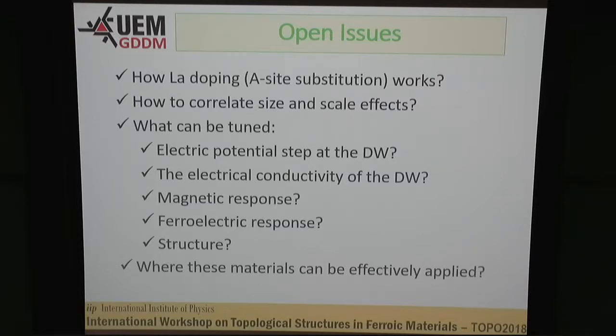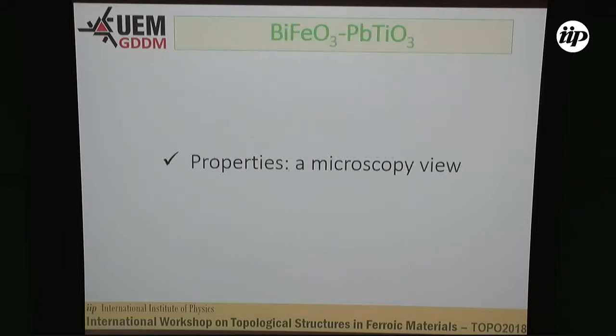When we did this, we still had a lot of questions to be solved. How does lanthanum doping, or generally A-site substitution, work in this kind of material? How to correlate size and scale effects here? And the most important, what can be tuned in this case? The electrical potential step at the domain wall, because it's an interesting problem for new generations of electronic materials, the electrical conductivity of the domain walls, the magnetic response, the ferroelectric response, and the structure, where these materials can be effectively applied. To do this, we try to see microscopically what is happening with our sample.